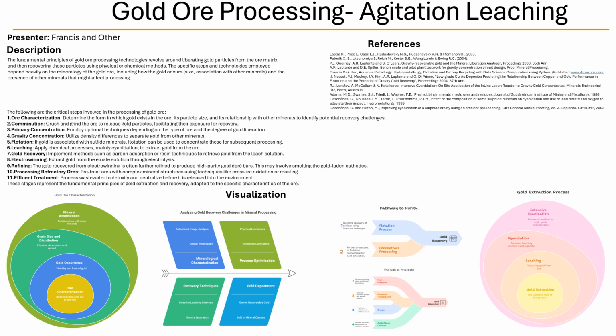Pretty much. And that's why the source material talks about the importance of preparing multiple polished sections of the ore for analysis. Like you might need 4, 5, even 6 sections just to get a statistically representative sample. So it's not just one quick peek under the microscope, it's a whole process, right? Yeah, it is. And if the ore grade is really low, then you might even need to use concentration techniques. These are essentially ways of separating the heavier minerals, including the gold, from the lighter gangue minerals. Ah, so it's like panning for gold, but in a super high-tech lab. That's a good analogy. You're using things like heavy liquids or special centrifuges to separate the gold based on its density.